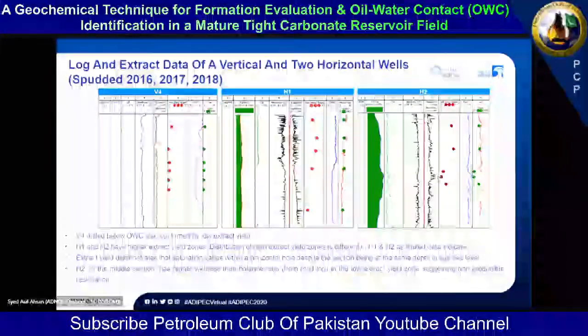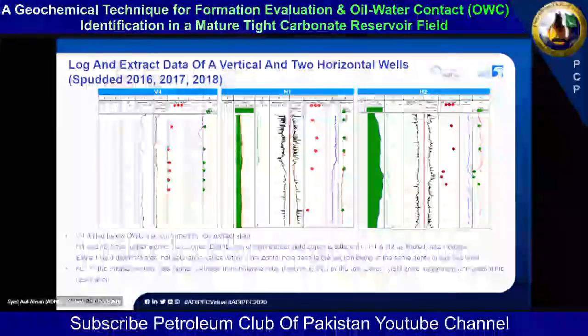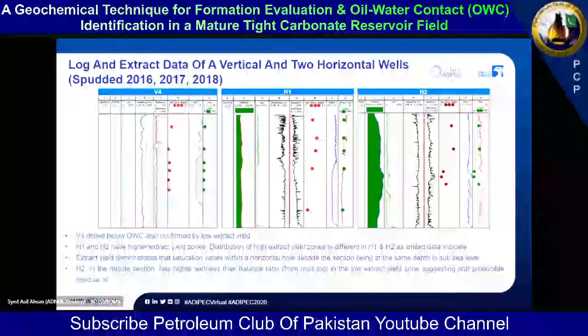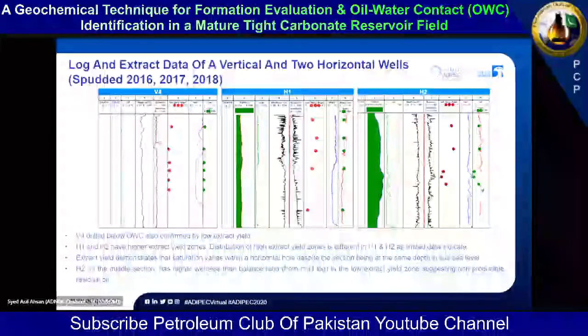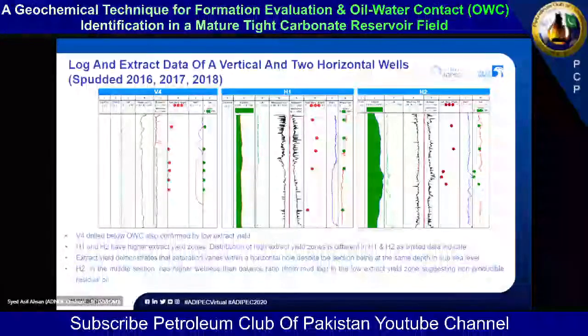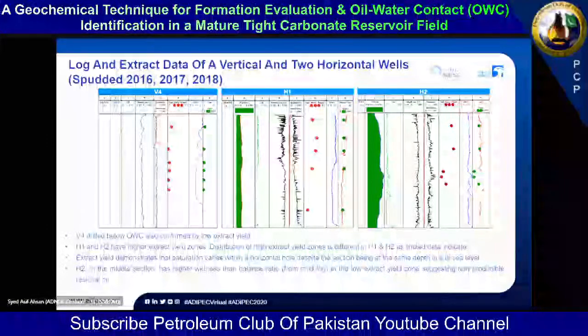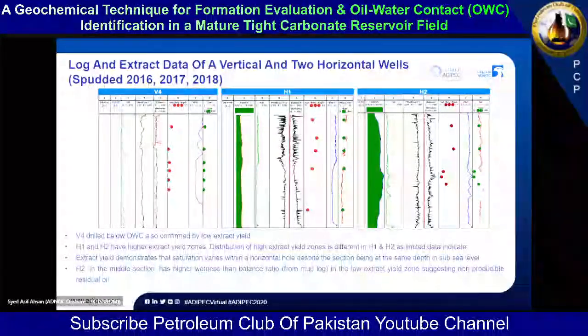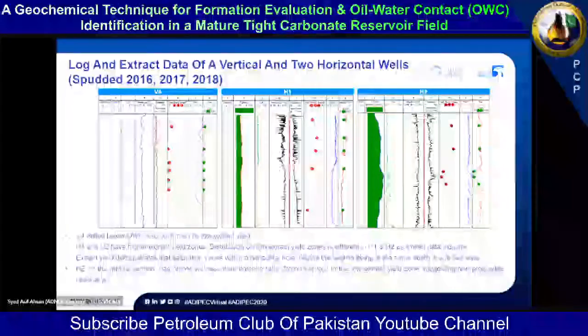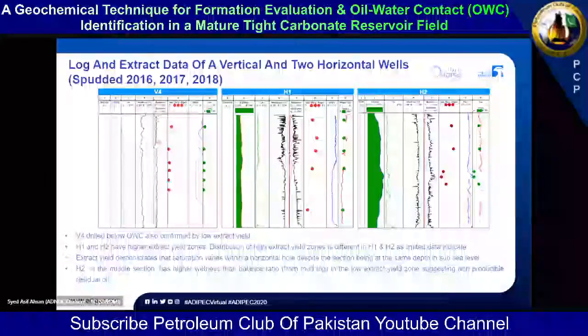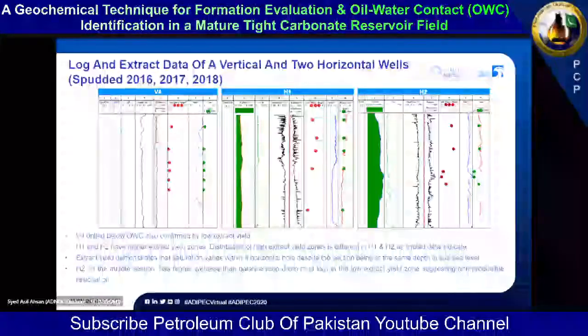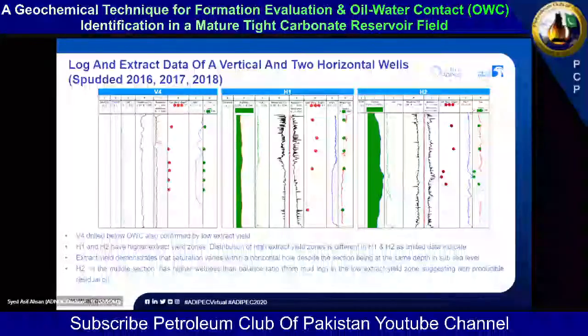So even the mud log data is showing, with its increased wetness ratio, that there is a non-producible oil, which is also confirmed by low extract yield. So within a given horizontal hole, which in this case is 3,000 feet, we are able to see the value of this data despite very few samples. I mean, only 5 samples for 3,000 feet of the section, and yet you are seeing the variation in the extract yield in this horizontal section as well. So where you want to complete your wells in the horizontal section, and when you will be producing this well, of course, the producing strategy and completion strategy should take into account what data you see. And we believe that this data is providing valuable information in terms of completion strategy for horizontal wells.